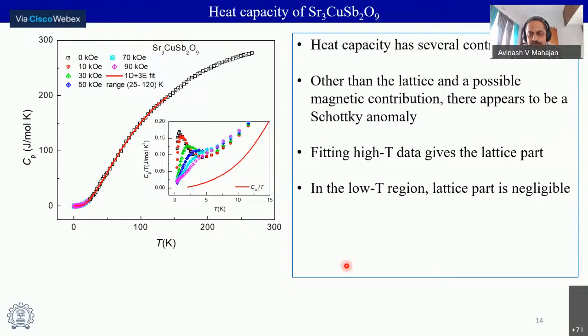Okay, the other piece of evidence is from a bulk measurement, which is the magnetic heat capacity. So one measures the total heat capacity, and one wants to extract the magnetic heat capacity out of that. So one has to somehow subtract out the lattice part. There might also be a Schottky term because of some two-level features in the system, because there are some free spins present. So generally, it's not very straightforward to extract the magnetic heat capacity. However, fortunately, in this low temperature region, the lattice part is really, really negligible. And if there's any magnetic part, it stands out. Okay, so one also needs to take care of the Schottky anomaly.